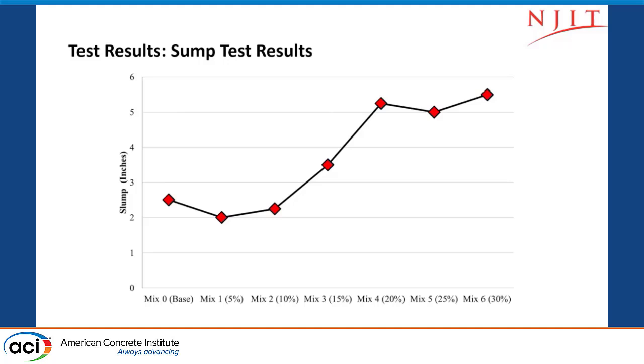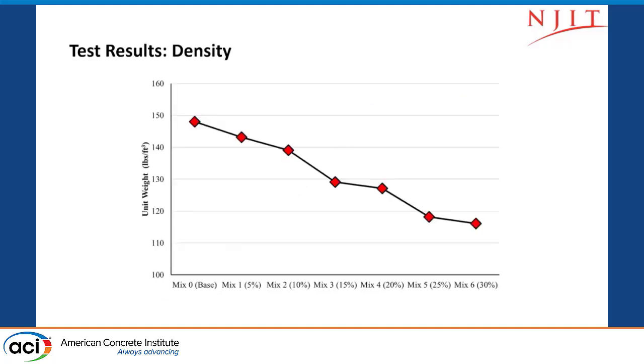And on the left-hand side is the mix, which is the base mix. And then after that, we did the replacement by weight again for fine aggregate: 5%, 10%, 15%, 20%, 25%, and 30% fine aggregate by weight. And we can see that the slump is increasing by increasing the percentage of biochar replacement.